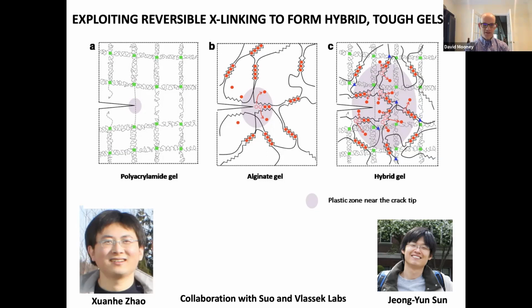And so what he and Suo proposed was that if one created interpenetrating networks that combined a covalently cross-linked network that would impart some level of strength and the ability to transfer stresses across large volumes of a material, with the energy dissipation properties of these physical crosslinks, one could potentially create a large plastic zone near a crack tip that could dissipate significant quantities of energy and significantly toughen the hydrogels. So they had proposed this. They actually went on to demonstrate this idea really convincingly.